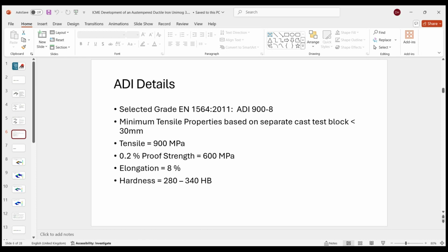Obviously, what we said was a design in ADI, and this is the grade that they decided to specify, ADI 900-8. This is a European norm or the ISO norm. You can see here the typical properties from a separately cast test bar. This is a Y block of 30mm section, with a tensile strength of 900 megapascals, a yield strength of 600, and elongation of 8%. There's also the ASTM standard, but obviously we're dealing here with a European customer, mainly for the European market.